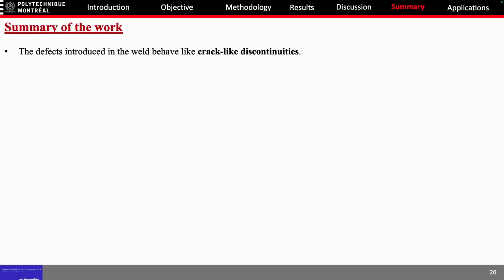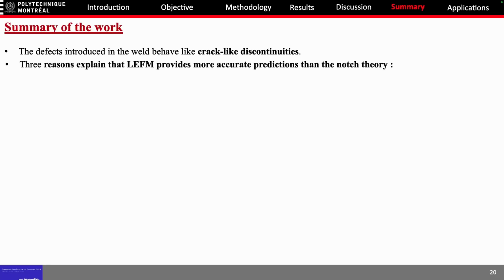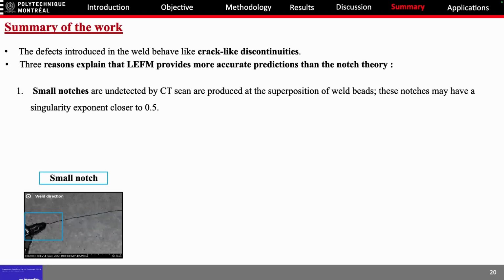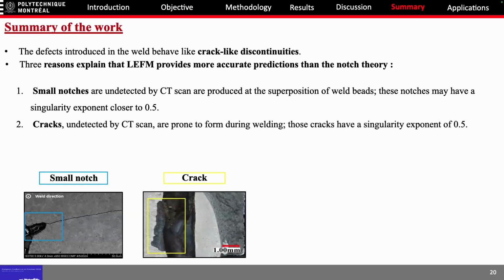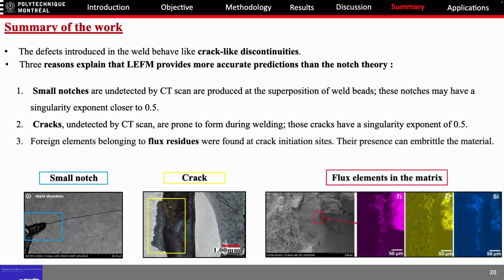So, summary of the work. The defects introduced in the weld behave like crack-like discontinuities, and three reasons explain why LEFM provides more accurate predictions than the notch theory. First of all, small notches undetected by CT scan were produced at the superposition of weld beads, and these notches may have a singularity exponent closer to 0.5. Then, cracks undetected by CT scan are prone to form during welding, and those cracks have a singularity exponent of 0.5. And like I mentioned on the last slide, foreign elements belonging to flux residues, such as zirconium, titanium, and silicon, were found at the crack initiation site, and their presence can embrittle the material.